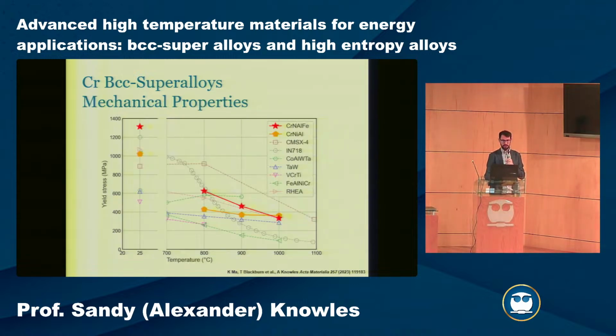We then also were looking at the mechanical behavior of these things. So this is, again, relatively simple alloys. We have 4 elements: chromium, nickel, aluminium, and a certain amount of iron in order to tune the microstructure. And then we can, again, get to very high yield strength at high temperature. So we can get things that are competitive, in the case of about 3 years of work, with 30, 40 years of nickel superalloys development, which is really exciting. So we're there in terms of strength.